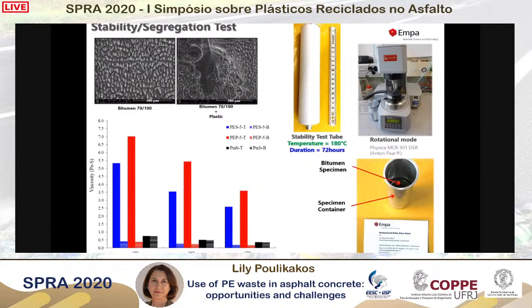Now I'm going to show you some microstructures that were done using electron microscopy. On the top left of the screen you see that when the binder is exposed to the electron beam, it forms a microstructure. On the left-hand side, we have the base bitumen. On the right-hand side, we have the base bitumen with plastics. So we see that the plastics did not disappear. They are present in our binder, even though it's above their melting temperature.